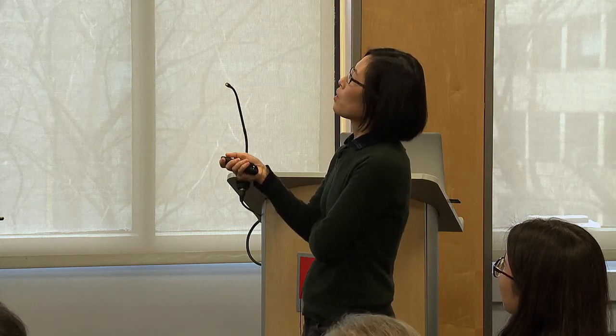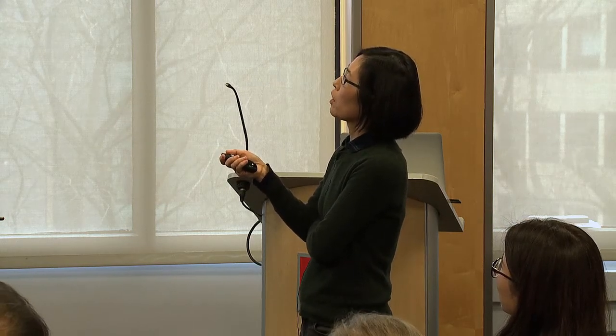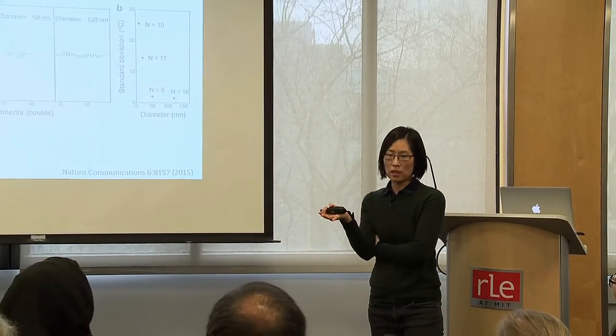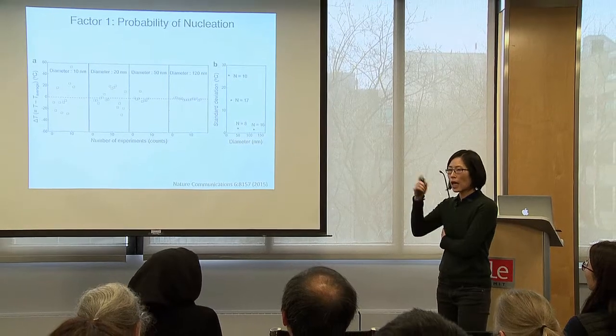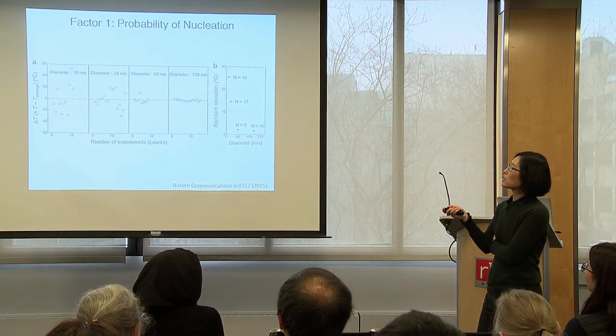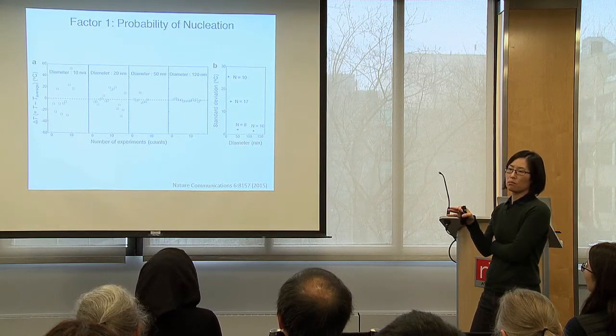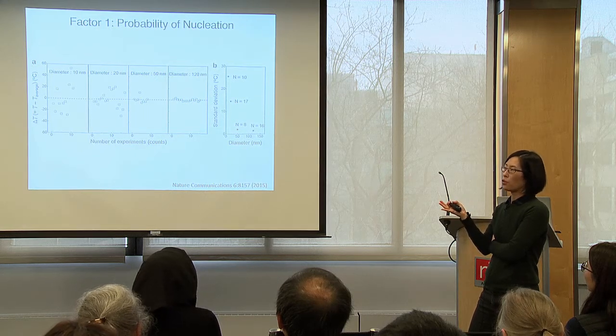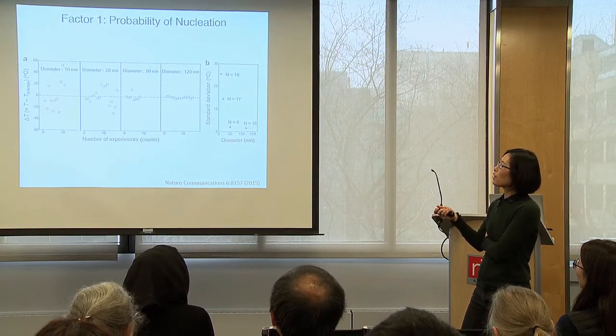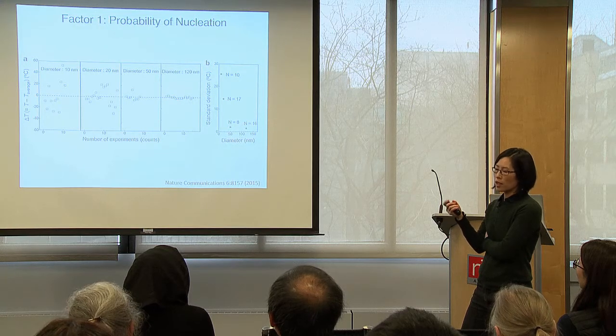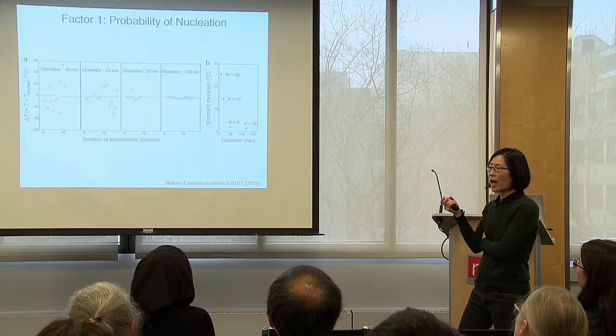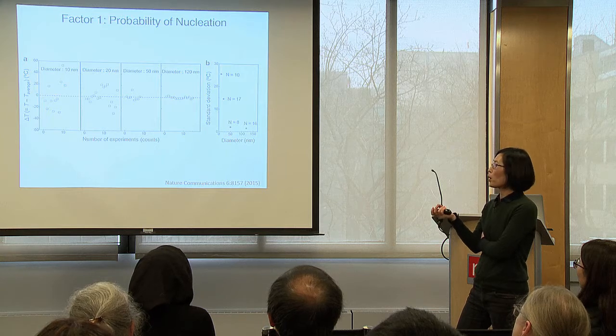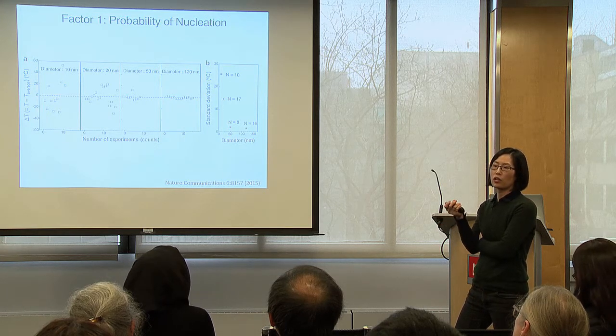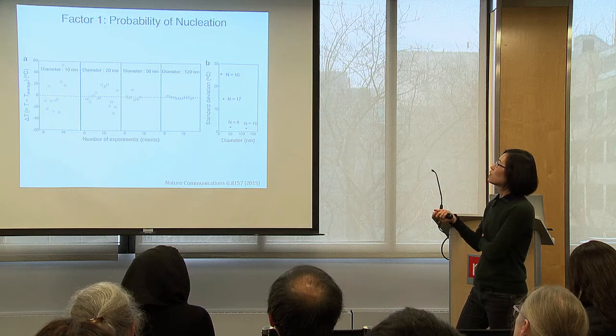This is an indirect way to verify this. For larger diameter rods, let's say 50 or 120 nanometers, we're going to assume that you will always have some nuclei present. If you always have some nuclei present as we repeat the experiments, the crystallization temperature should be steady because you have nuclei to begin with. If you don't have nuclei, let's say for smaller rods, since nucleation is somewhat of a stochastic, probabilistic process, there should be a scatter in your crystallization temperature. And that's what we see here.